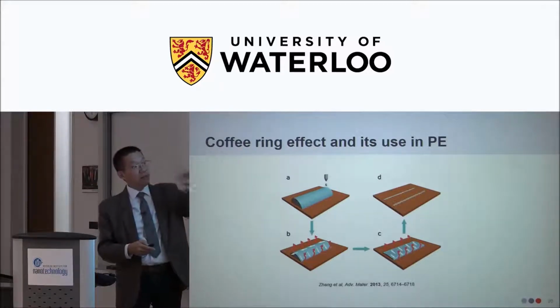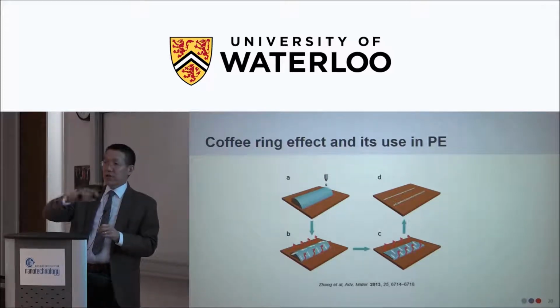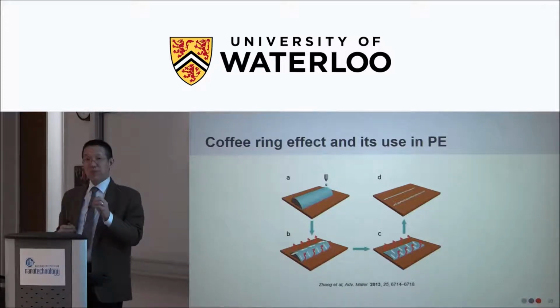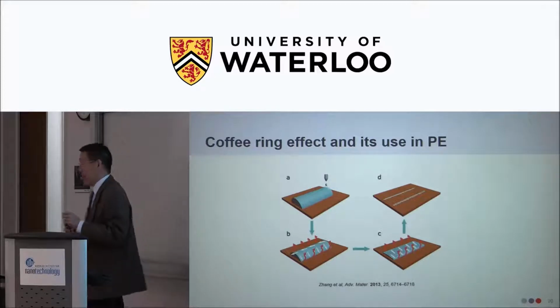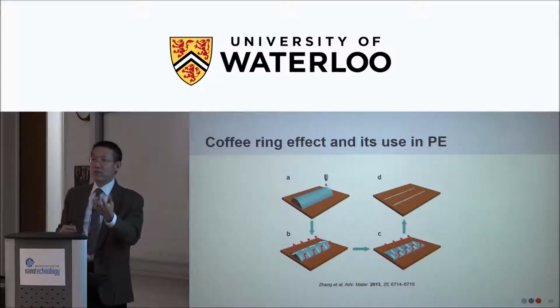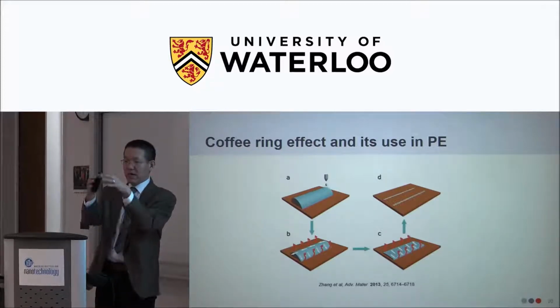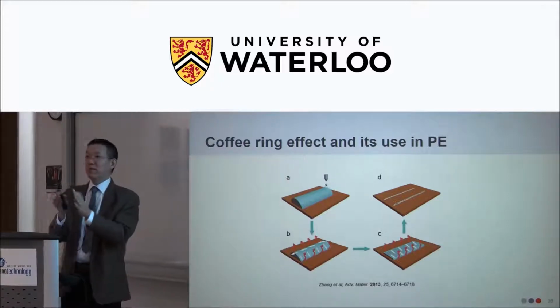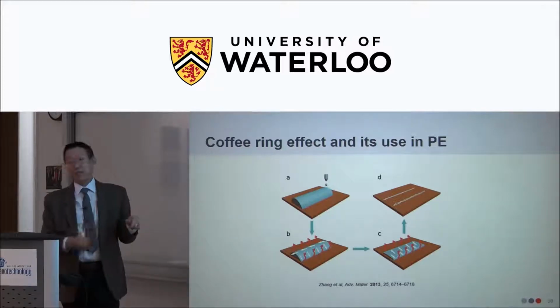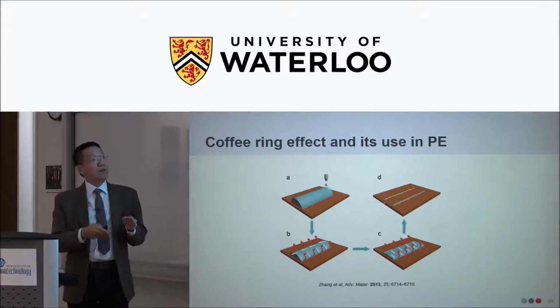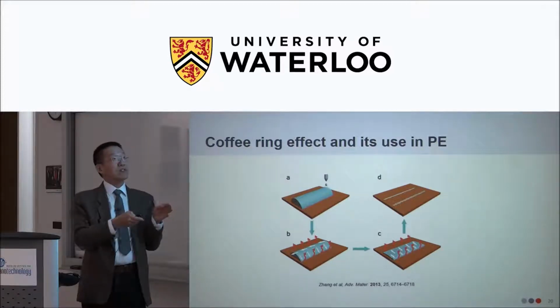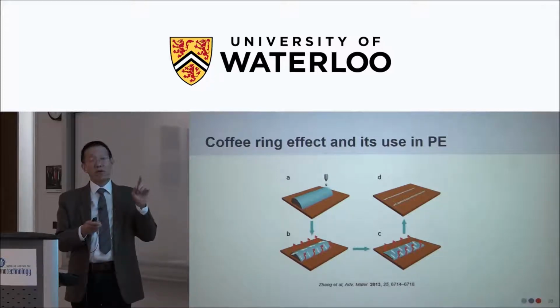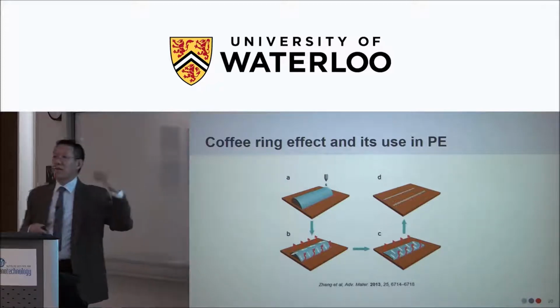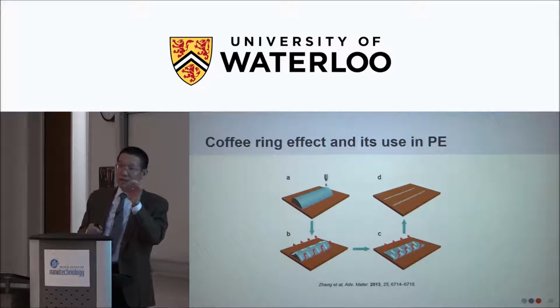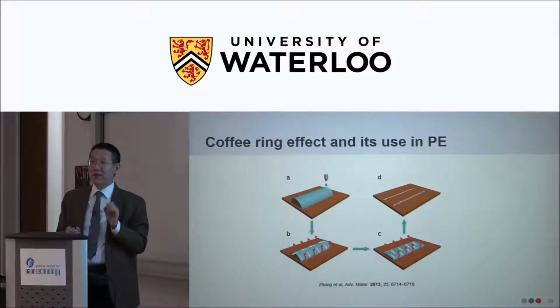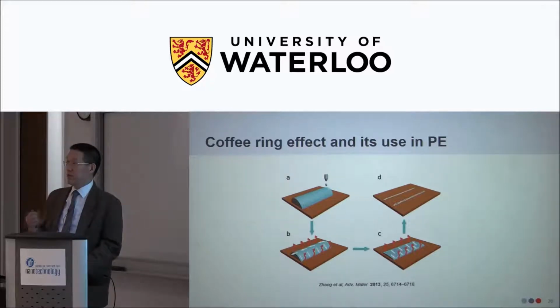One way to use this to our advantage is demonstrated by this paper, published by one group in China. It's a really diluted silver ink you print on the substrate. When you use inkjet printing, the narrowest line you can print is probably about 40 micrometers wide, because the nozzle we use typically gives you a 25 micrometer diameter droplet. When you put it on the surface, it's roughly 40, 50 micrometers. So that's 50 micrometers, for example. And when it dries up, using the coffee ring effect, all these nanoparticles in the liquid will be pushed to the two sides. And you have two very narrow lines with a pitch resolution of 50 micrometers. But the conductance is limited because the line is really, really thin. Nevertheless, that's a way to use this phenomenon to reach high resolution printing.